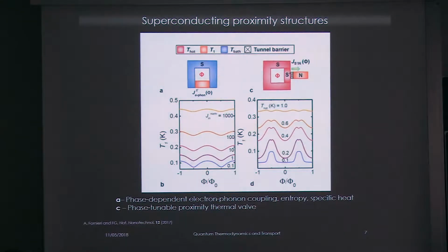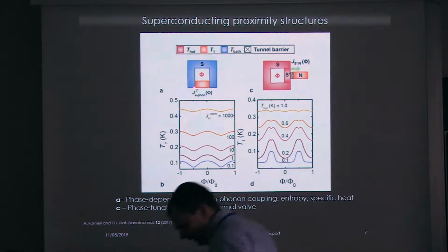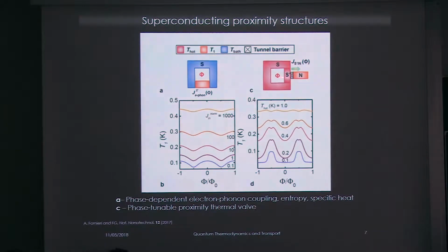Then, if we go back to proximity structures, I was saying that they are very promising in the sense that we don't need a genuine superconductor to implement them. What we need is a material that does not possess any superconducting properties, but is in intimate contact with, for instance, a superconductor. In this case, we have a normal metal here in the middle, which is laterally contacted by a superconducting ring. Thanks to this contact, and suitable geometrical conditions, with the flux we can control the amount of superconductivity induced in this part. And as I was saying, the density of states and other important properties of the metal become phase dependent in this case.